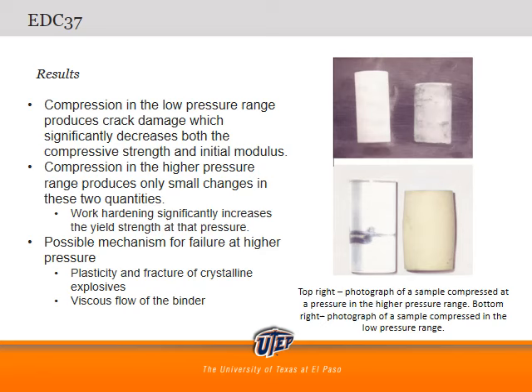Compression in the higher pressure range produces only small changes in these 2 quantities, and work hardening significantly increases the yield strength at these pressures. Possible mechanisms for failure at high pressure include plasticity and fracture of crystalline explosives, as well as the viscous flow of the binder causing debonding and plastic flow. To the right, you can see pictures of the test specimens before and after compression. The top picture is a sample at the higher pressure range, and the bottom shows a sample at the lower pressure range.